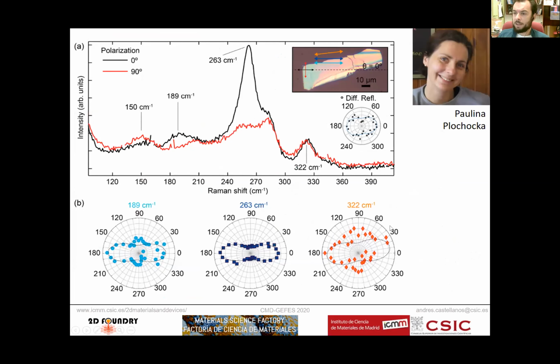We have also done Raman measurements with the help of our colleague Paulina Plochocka at the CNRS in Toulouse, France. And this franckeite system also shows a highly linearly polarized Raman emission. So basically we excite this sample with polarized light, and we use an analyzer, and then we can monitor the polarization dependence of these different peaks of the system. These are the 4 main peaks of franckeite, and we can see how these different peaks have a certain anisotropy that is closely related to the anisotropy that we see in the differential reflectance for the same flake. Again, the little misalignment between the differential reflectance and the Raman measurements can be due to the experimental uncertainty in aligning the samples in the different experimental setups.